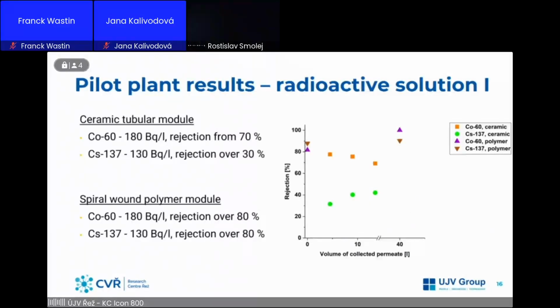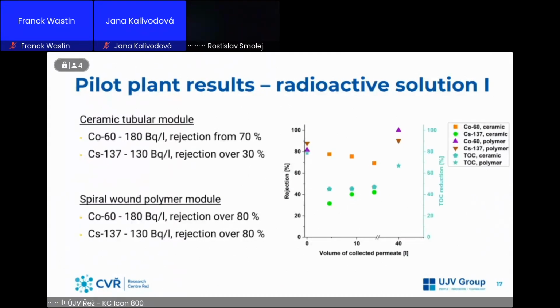The polymer module performed much better, even in comparison to the non-radioactive model solution. Also, the cesium rejection rose to over 80%, which we're very happy about. What both membranes did, they also reduced the total organic carbon levels. The ceramic one from 40% and the polymer membrane from 65% and higher.